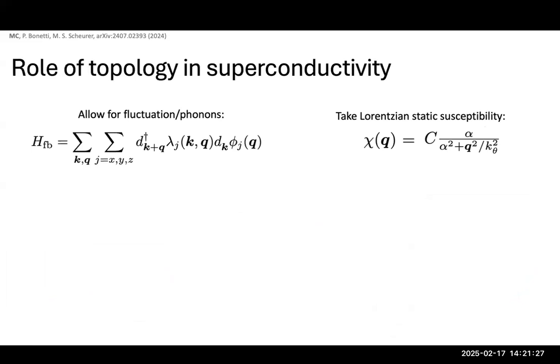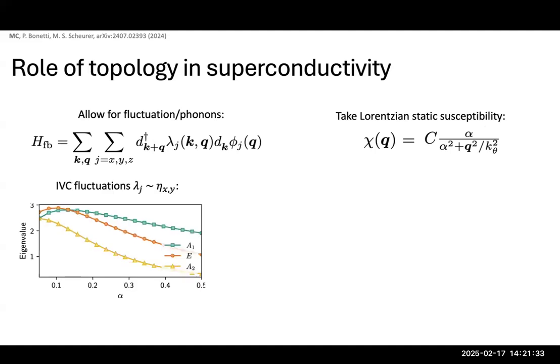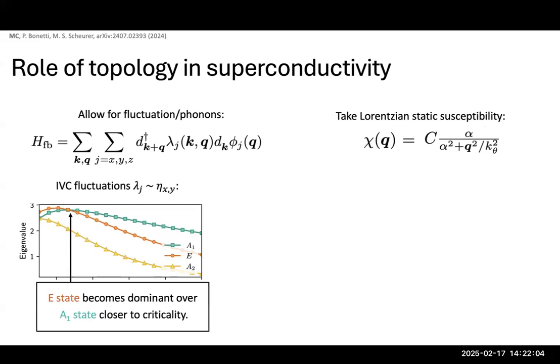And now we can see something interesting about the role that the fact that we're pairing these states in a flat band. Okay, so if we take this IVC order parameter and fluctuations of it, and then we vary the strength of this Lorentzian parameter alpha, so you can think about kind of physically you're tuning either closer or further away to this critical point, for very small alpha, when this is a narrow Lorentzian potential, the E state, the nematic state, begins to win. And the reason for this, why this makes such a difference, essentially comes from these form factors.